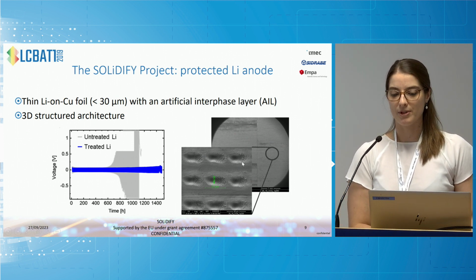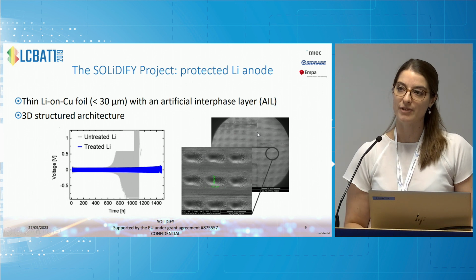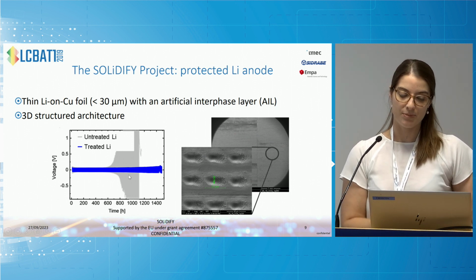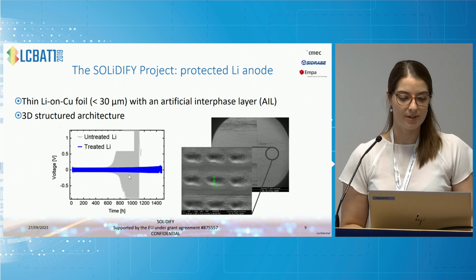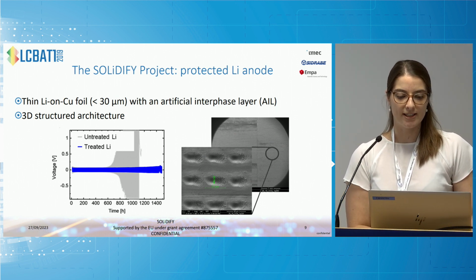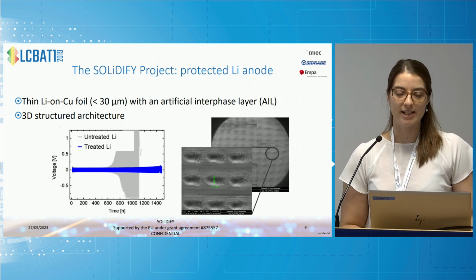And this, for example, is using laser ablation that we've developed at IMEC. And you'll see that with the treatment, for example, it could be a lithium nitride treatment, we can improve the lifetime of the anode as well.